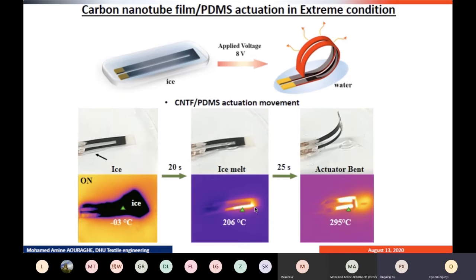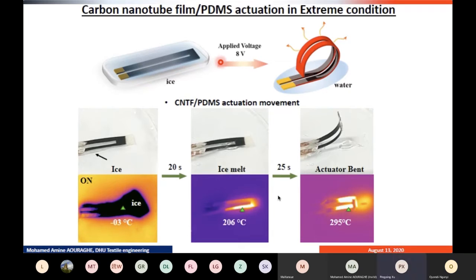We also studied the actuation behavior of the fabricated CNT film PDMS actuator by dipping it into water and freezing it, as shown in this figure. We applied a voltage of 8 volts to activate the actuator in these circumstances, and after 20 seconds the ice starts melting and the actuator starts to bend after 25 seconds, as shown in the figure, with the increment of temperature, which demonstrates the wide utility of the proposed and fabricated actuator.